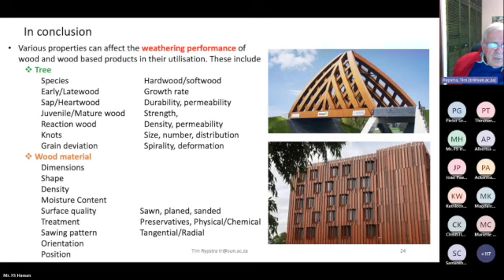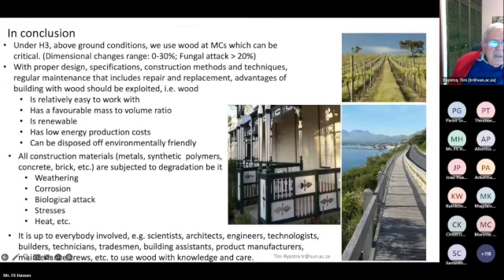And then with wood material, dimensions and shape of wood, a flat piece versus a square cross section, density very important, moisture content, surface quality, whether it's sawn, planed or sanded, the treatment, whether it's been preserved or treated with physical or chemical treatments, sawing pattern, whether it's radial or tangential, orientation and position, and then in the last slide, something in conclusion there. So under H3, above ground conditions, we use wood at MCs, which can be critical, and